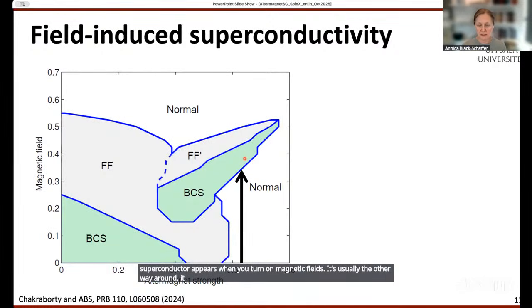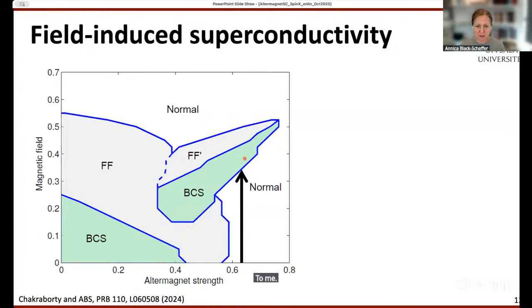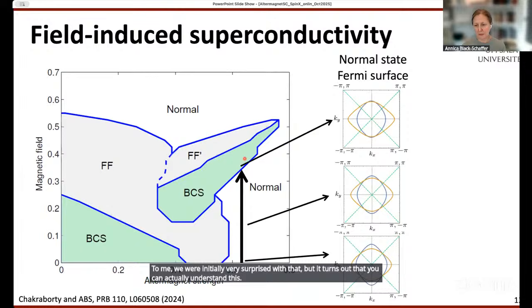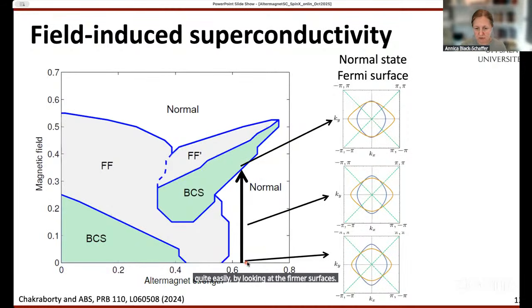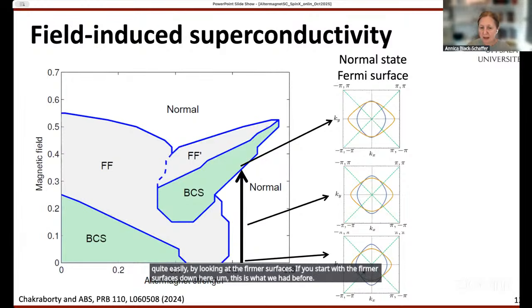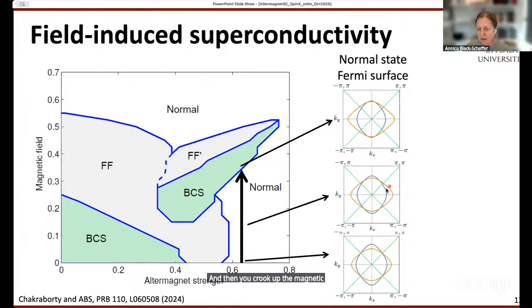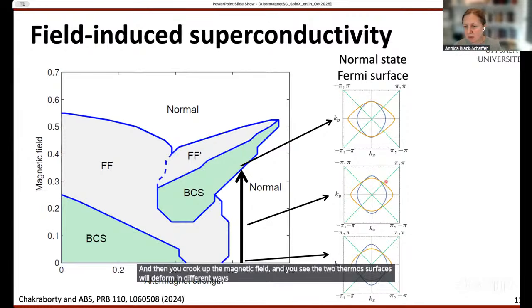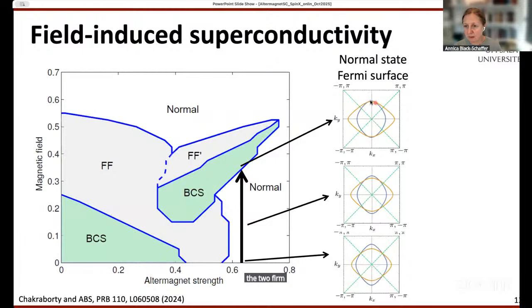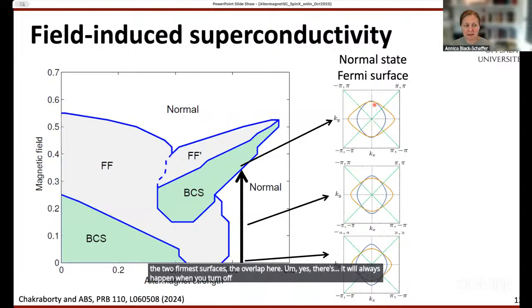It kills superconductivity. So we were initially very surprised by that, but it turns out that you can actually understand this quite easily by looking at the Fermi surfaces. If you start with the Fermi surfaces down here, this is what we had before, and then you crank up the magnetic field, and you see the two Fermi surfaces deform in different ways. Eventually you're going to have the two Fermi surfaces overlap here.